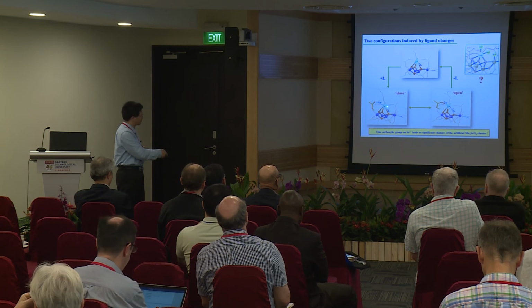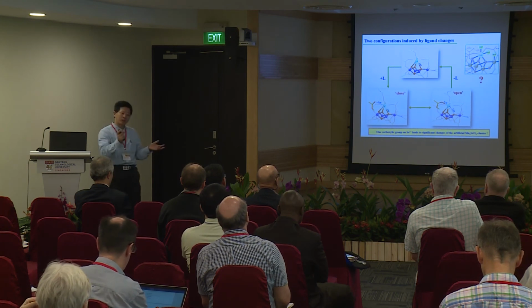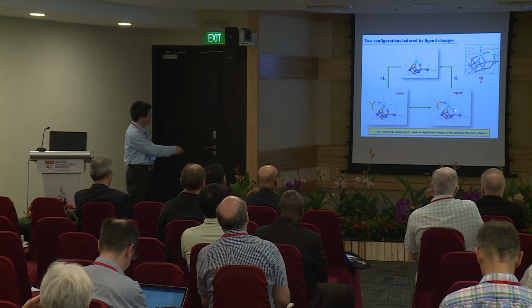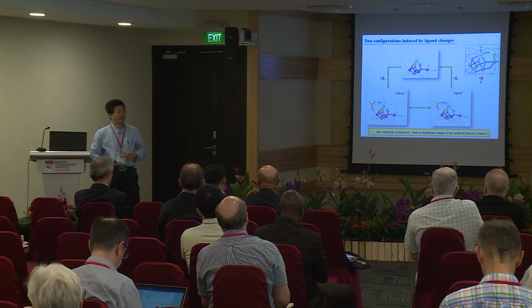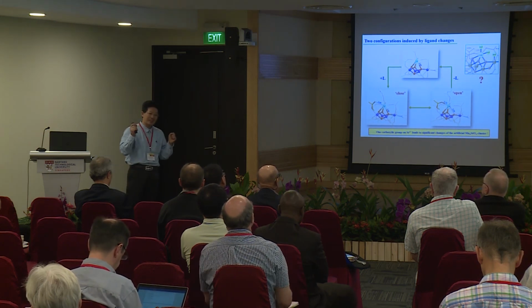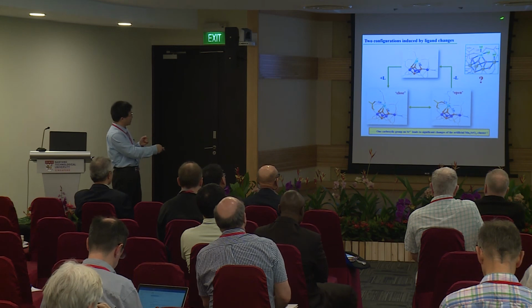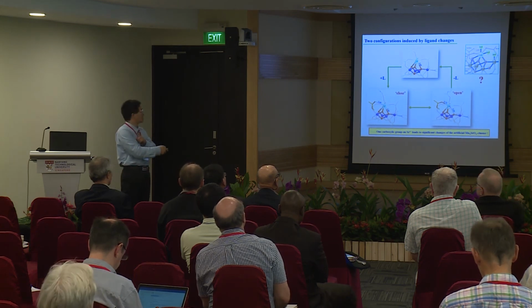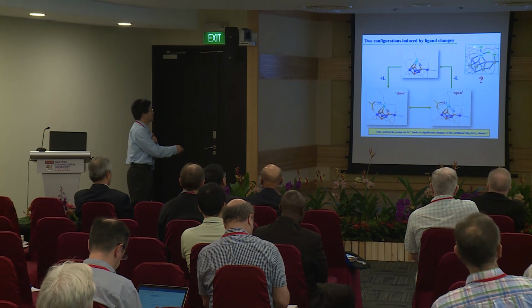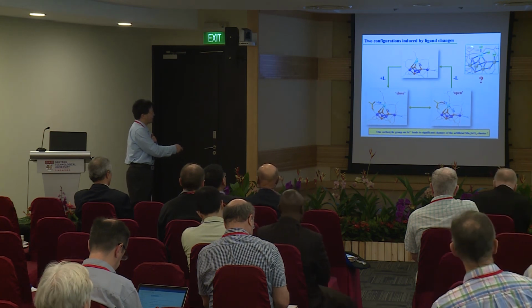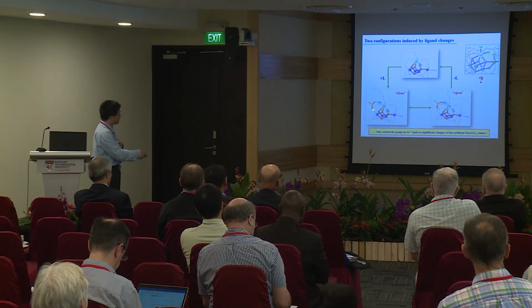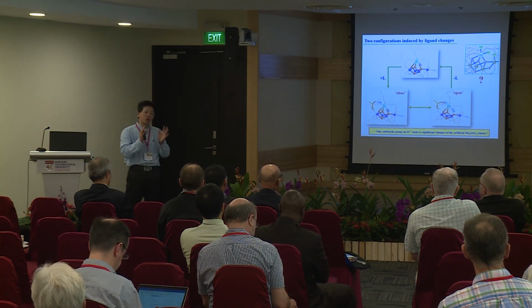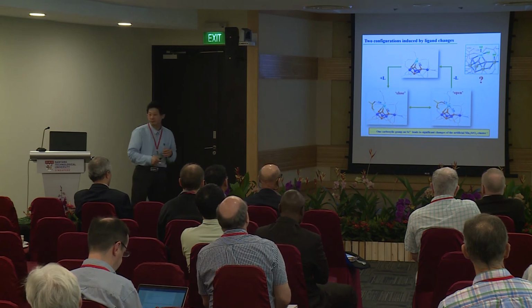This is closed cubane. The distance is 2.9 angstrom, and sometimes can be 2.7 angstrom. But now it is 3.1 angstrom. So the closed cubane just changed to open cubane. The interesting thing is, in the OEC, there is one special ligand, glutamate 189. This is a free oxygen, which is far away, 3.1 angstrom from the calcium or strontium, just like these ligands. So probably this kind of change could take place in the natural system as well.